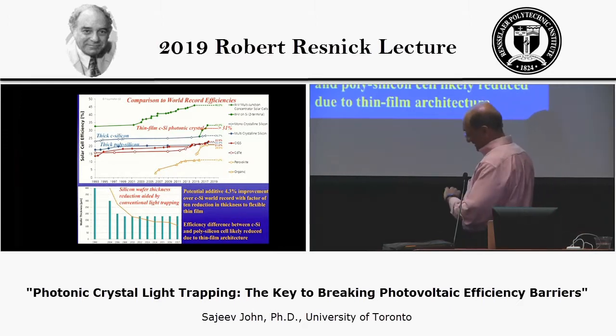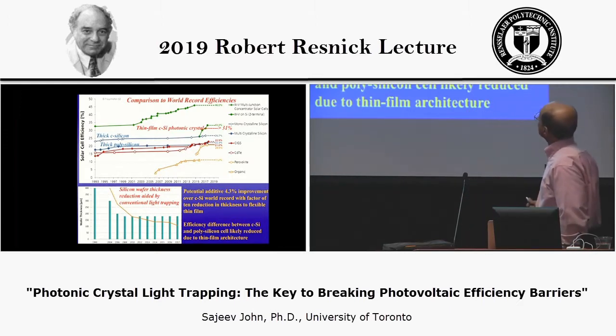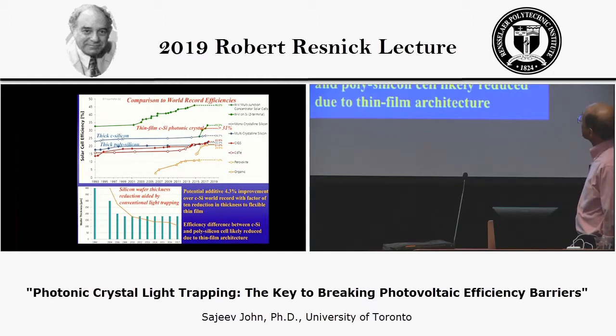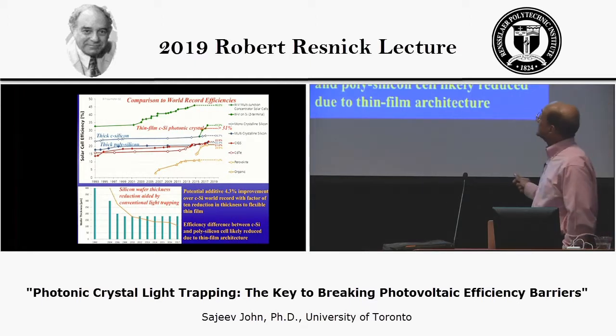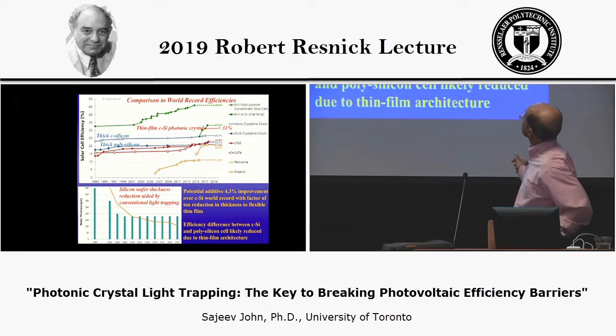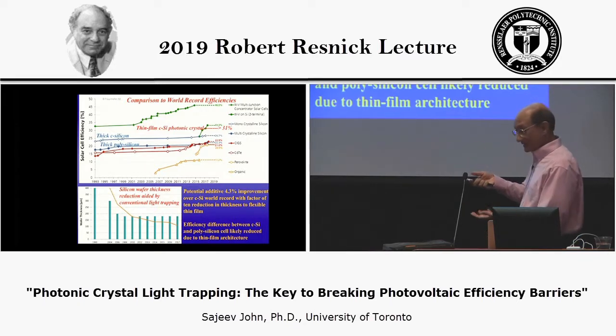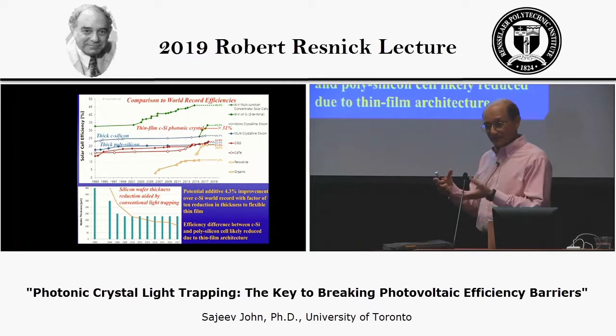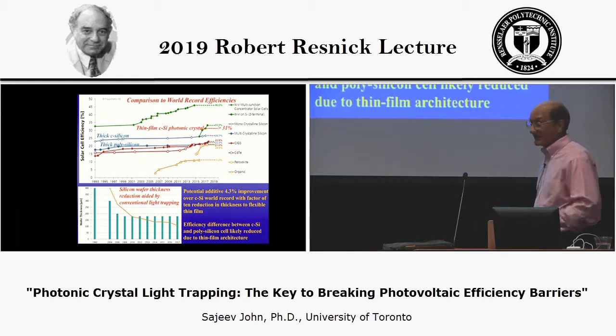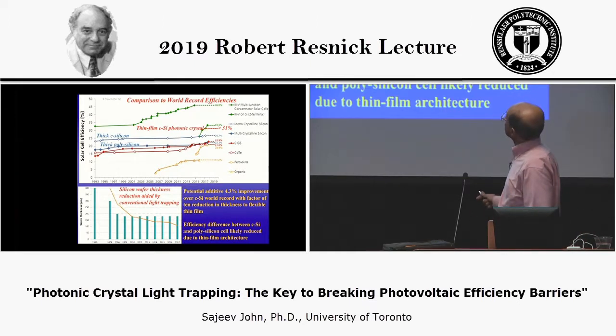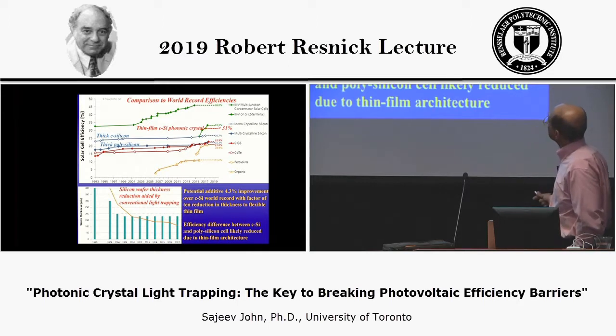Okay, so where does this all stand relative to world record solar cells? Of course, if you go to multi-junction cells, the highest efficiency is up to 46%. That involves about 4 different materials stacked on top of each other, and that is with a solar concentrator that creates 1,000 times the natural solar intensity to reach those sort of efficiencies. But the more important curves are the ones down here that consist of a single material.